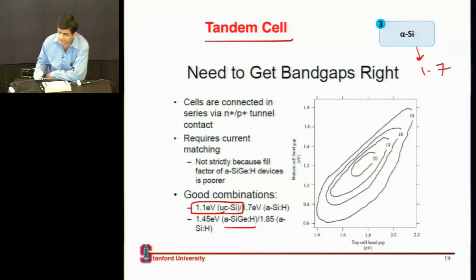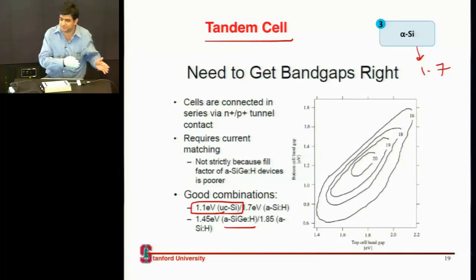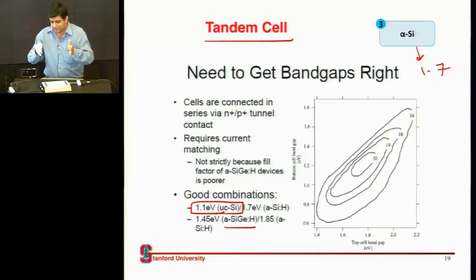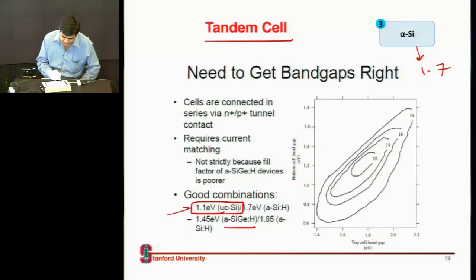So this microcrystalline silicon is somewhere close to a polycrystalline. So you have a crystalline material, you have a microcrystalline material, you have a nanocrystalline material, and you have amorphous material. So this microcrystalline material is something which is crystalline but has a grain size on a micron scale. So it's close to a polycrystalline kind of material, where the band gap is that of a single crystalline material. So the band gap is 1.1, but it still has grain and it has defects.